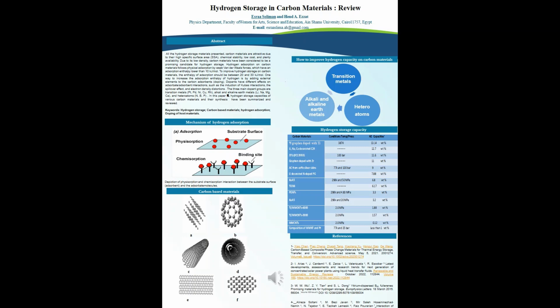Hydrogen adsorption on carbon materials follows physical adsorption by weak van der Waals forces, which have adsorption enthalpy lower than 10 kJ per mole. The enthalpy of hydrogen adsorption should be between 20 and 30 kJ per mole. So finally, to increase the adsorption enthalpy, we should add external elements to the carbon adsorbent such as transition metals, alkali and alkaline earth metals, and heteroatoms. These metal dopings can resolve the problem of weak binding between hydrogen and the host materials, and thereby enhance the storage capacities. And the heteroatoms could tune their electronic and catalytic properties that make the carbon-based materials prospective for this application.